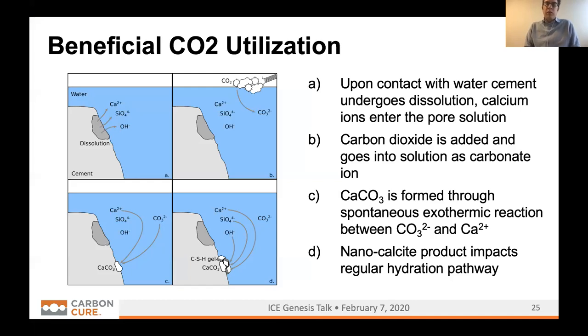What happens when the CO2 interacts with the concrete? Well, we can back up a little bit and say the concrete has started to mix. We'll just talk about the cement phase here, but we have water and cement in contact. The cement itself undergoes dissolution, and ions start entering the pore solution, and the very preliminary phases start to form. But if you want to boil it down, we have calcium going into solution.